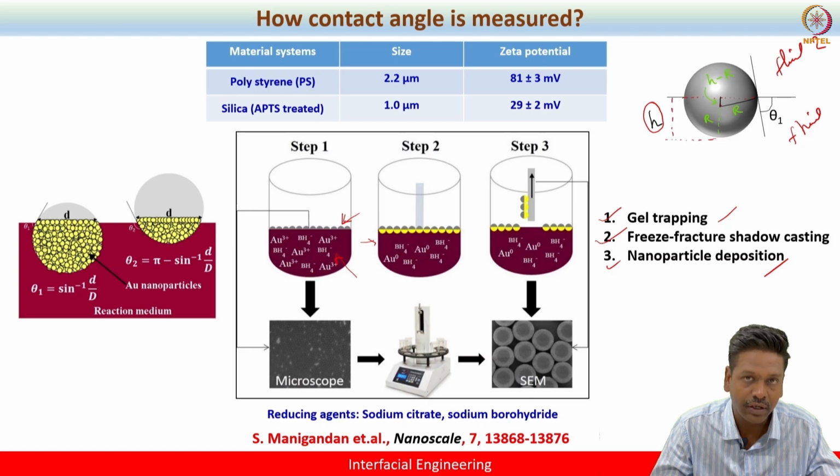So there will be electrostatic interaction between the positively charged, amidine functionalized polystyrene surface. Here we have taken polystyrene just as a representative system. Because the chloroauric acid carries a negative charge, there will be electrostatic interaction between the positive site and the chloroauric acid. So there will be a nice binding.